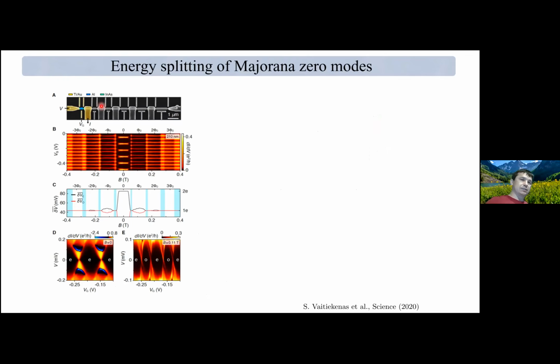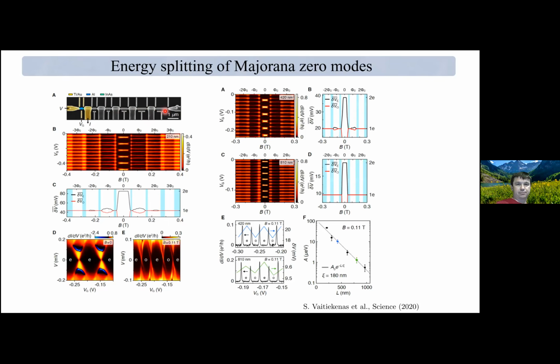So by using this full shell wire and by using these Coulomb blockaded islands of different lengths, one can test this hypothesis and see how this even-odd effect disappears as we make the system longer and longer. And so here is the data, and you can see signals. The position of these peaks tells us about these small differences in the even-odd effect. But ultimately, when we put everything together, one finds that this residual difference in the even-odd effect collapses on this exponential plot, which indicates that we have exponential splitting as a function of system length. So this gives us another independent confirmation that we are dealing with a gapped system, and we're dealing with these zero energy states that appear at the opposite ends of the wire.